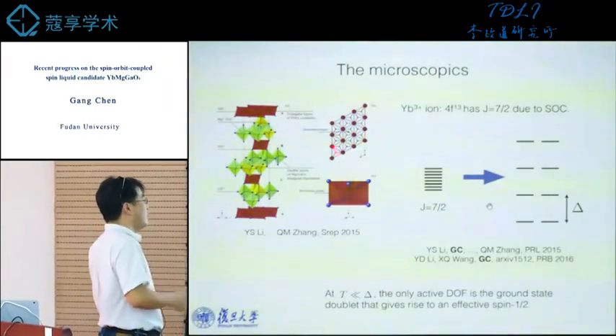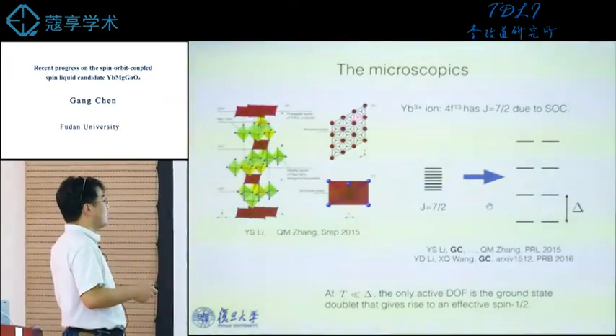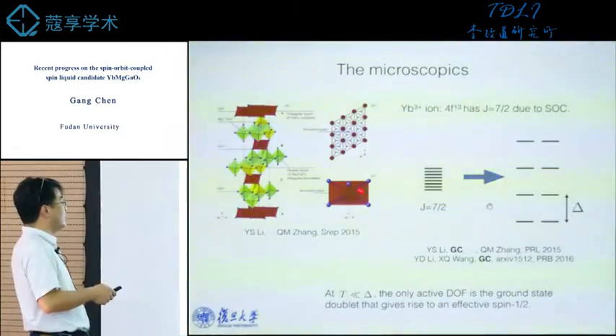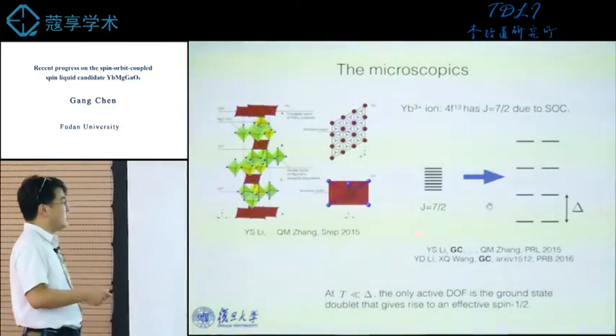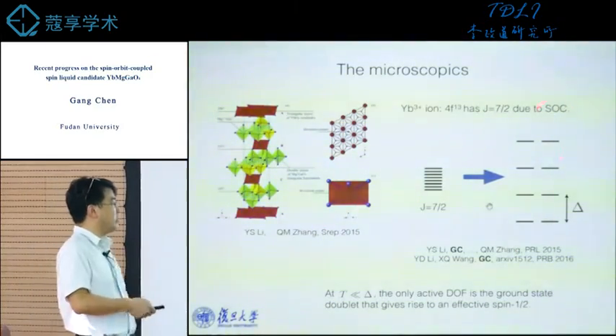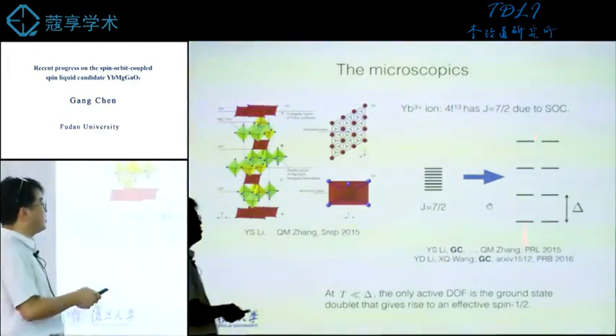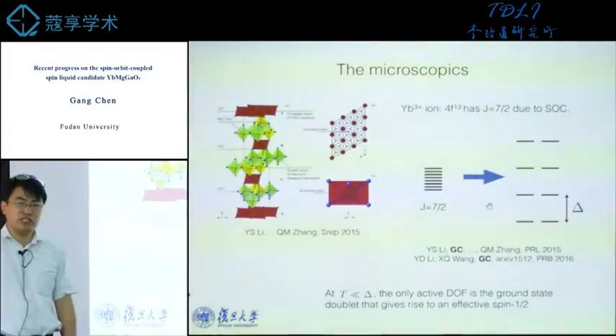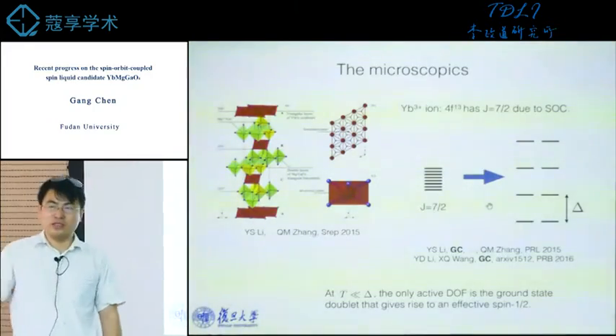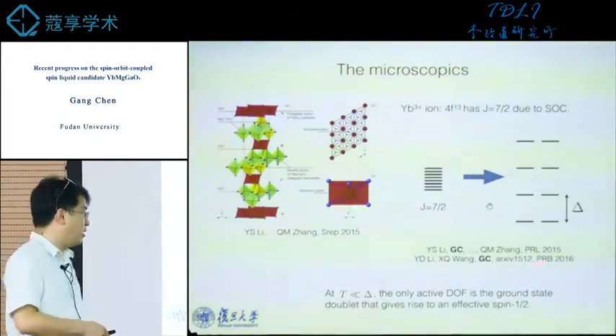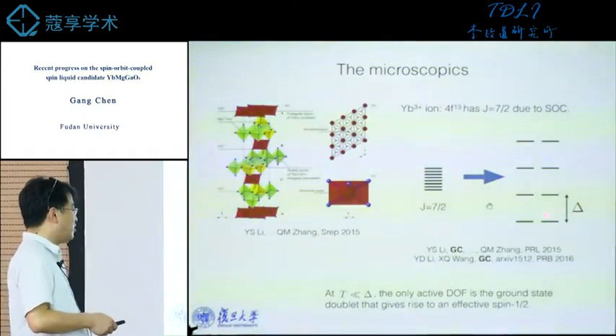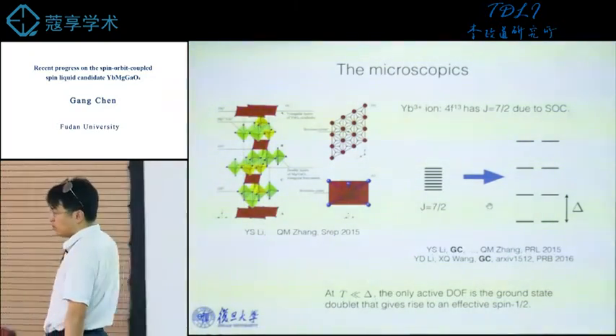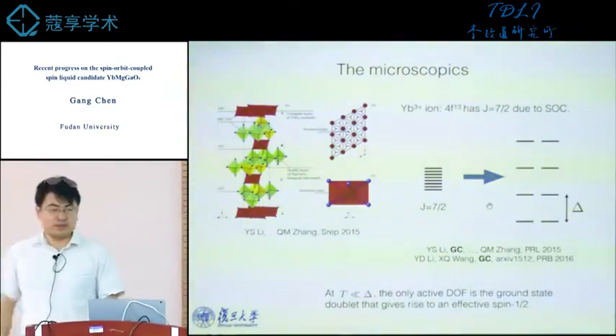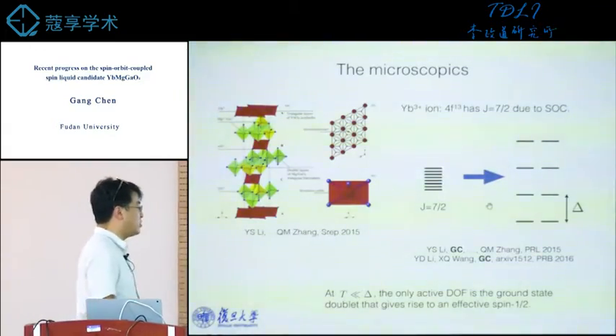So this is on a triangular lattice with a D3 point group. The total moment is J equal to 7/2, and under the crystal field it splits into these 4 doublets. Each of them is 2-fold degenerate. The 2-fold degeneracy is due to Kramers' theorem, so this is Kramers degeneracy. This gap is pretty large, on the order of 400 Kelvin. So the ground state doublet can be labeled as an effective spin 1/2.